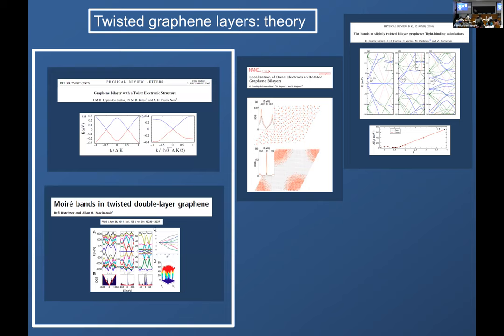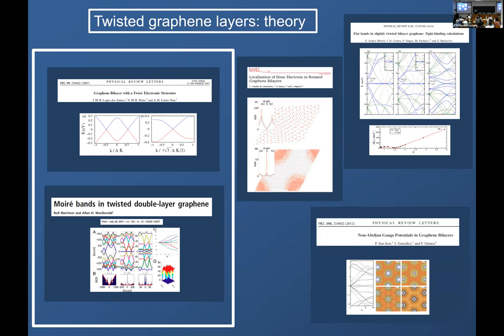The idea that twisted bilayer graphene were interesting started with tight binding calculations in about 2010. The generalization of the Dirac model people used to study the low energy properties of single layer graphene to twisted graphene is a continuum model, a k·p model. That model in 2010 was extensively studied by Allan MacDonald and Rafi Bistritzer in a famous paper in PNAS where, in agreement with tight binding calculations I just mentioned, they discovered that there were very flat bands at certain twist angles, and they were so flat that even the Fermi velocity, the effective Fermi velocity of these bands, went all the way to zero.